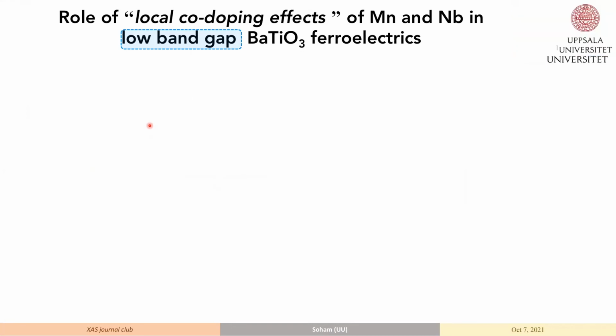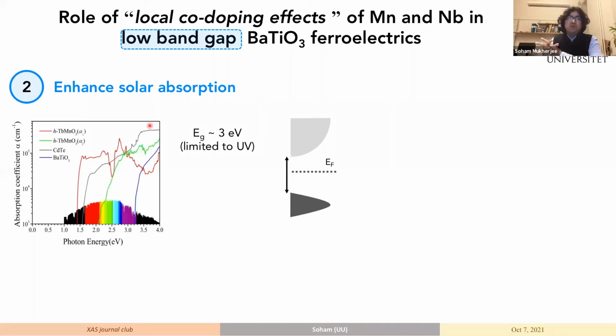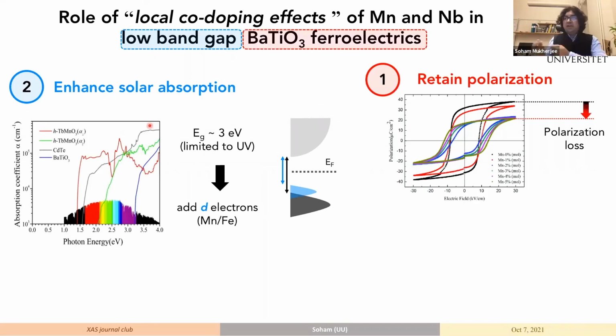So the title of this part is role of local co-doping effects of manganese and niobium in low band gap barium titanate ferroelectrics. And the aim for low band gap was because these titanates typically come with larger band gaps and cannot utilize the solar spectrum very effectively. So the trick was to put d electrons in the system so you can reduce the band gap. But it comes with a detrimental effect: you exchange d0 electrons with dn electrons, and it immediately leads to polarization loss because the off-centering of the titanium goes down and the long-range order breaks down.